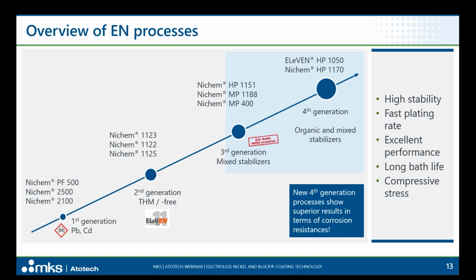And so we have developed the second generation of toxic heavy metal free stabilizers. And these are the 11 compliant processes, the Nichem 11 series, like Nichem 1122, 22, 23, 25. To improve the stability and the coating property of this generation, we developed the third generation where we added an extra non-metallic stabilizer to the system. And so we have developed the Nichem HP 1151, our best seller in the high P range, the MP 1188, our star in the mid P range, and our most bright mid P process, MP 400.